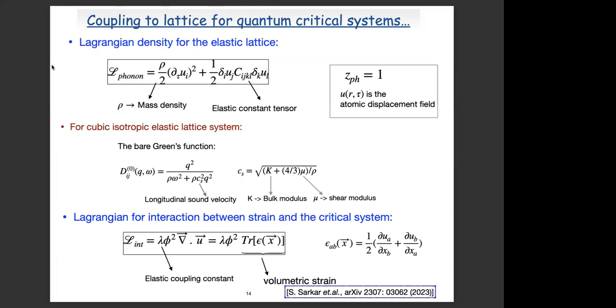Okay, so the Lagrangian density for the elastic lattice, or the phonon, is now given by this equation. Here you see that we have a dynamic part because we are at T equals 0, and this is basically similar to what we had earlier. And here C_ijkl is the elastic constant tensor. We have considered acoustic phonons, so the dynamical exponent for the phonon is also 1, and u is the atomic displacement. For our working purpose, we consider cubic isotropic elastic lattice systems, and dictated by this symmetry, the bare Green's function of the phonon modes becomes this, where c_s is the longitudinal sound velocity, given by this equation where K is the bulk modulus and mu is the shear modulus.